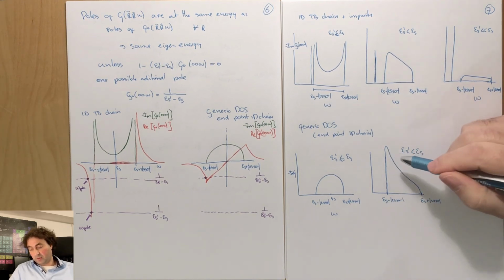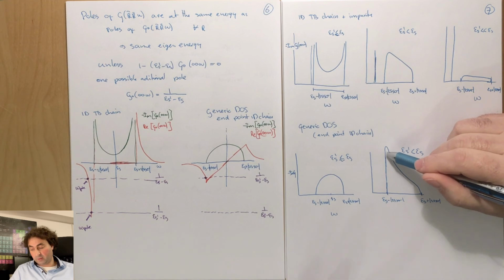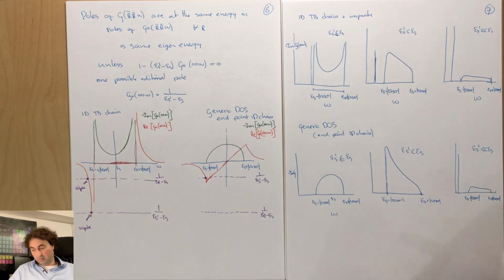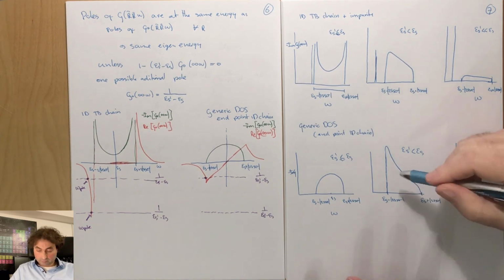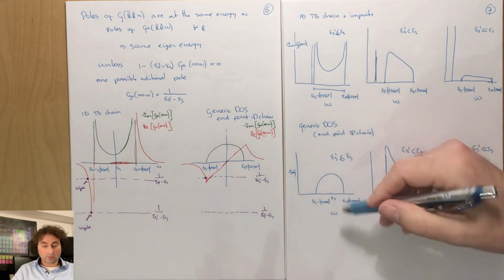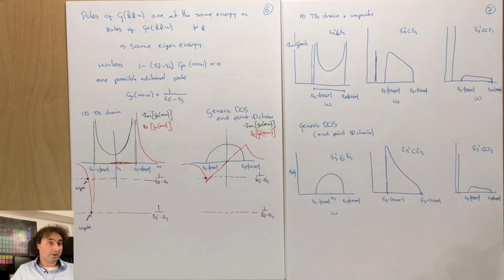But when the impurity potential is so weak still that you're still inside the continuum, then you enhance your local cross-section, but you still talk about states that will decay and propagate, such that you still generate your current and your electron hole pair that then flows through the wire and generates the photovoltaic current. So that's how you can optimize your solar cells, by putting in impurities or dyes into your system and have a strong impurity potential, much stronger than the dopants that you put in, but not too strong that it forms a locally bound state. So we want a resonance and not an exciton.